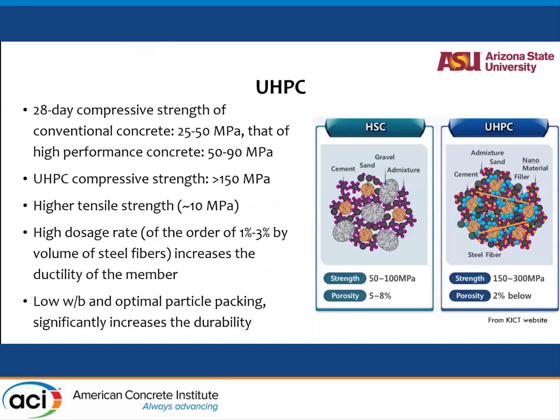So again, I'll do some customary introductions of UHPC just to get into the topic. Conventional concretes have about 25 to 50 megapascal compressive strength. We talked about high performance concrete quite a bit, with silica fume and lots of high performance bridge decks, and that's about 50 to 100 megapascal. And now we're talking about 150 megapascal plus, or 25,000 psi strength or more, for UHPCs. Tensile strength also is high, about 10-15 megapascal. You need quite a bit of steel fibers to get the ductility and the crack control that you need for such highly durable materials.